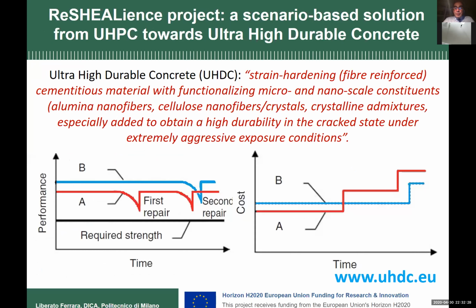So this is an ultra durable concrete that we designed to use, a strain hardening fiber reinforced cementitious material with functionalizing micro and nano scale constituents, because in these materials we added crystalline admixtures for self-healing, we added alumina nanofibers, cellulose nanofibers, and nanocrystals. For sure, we can obtain higher performance.